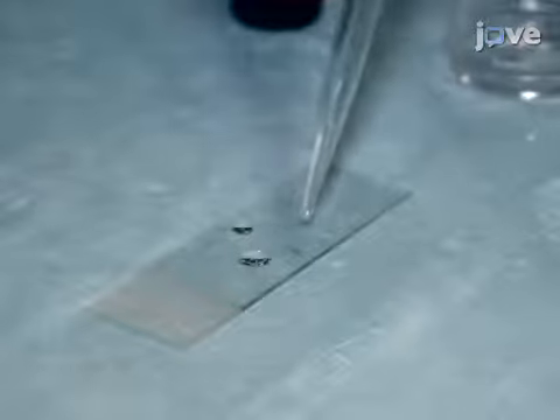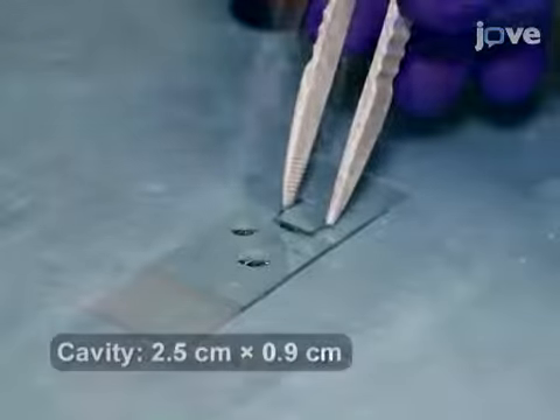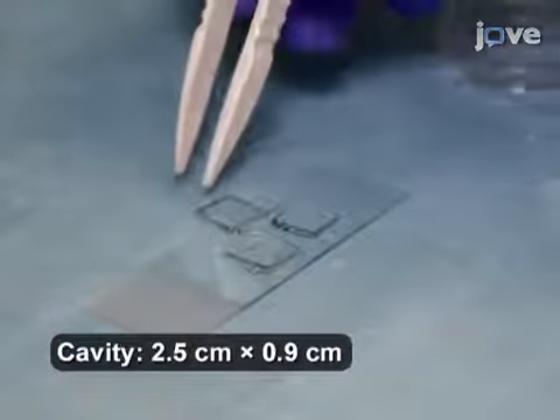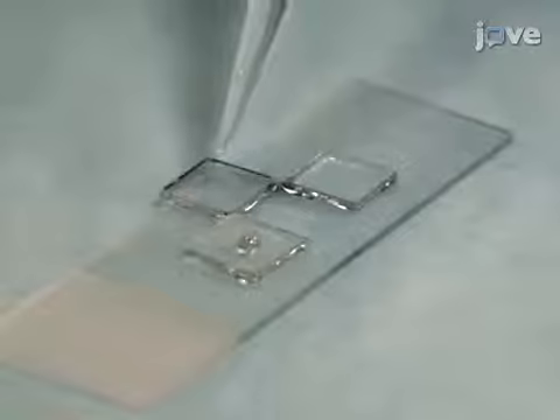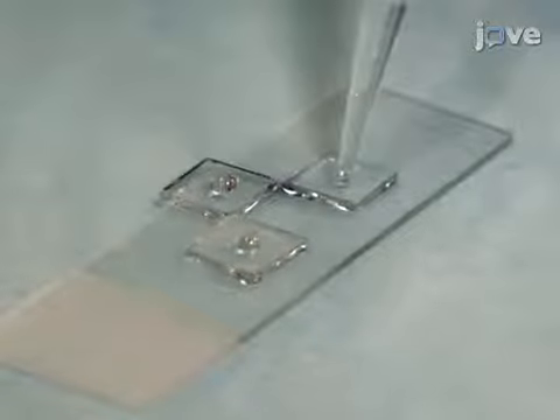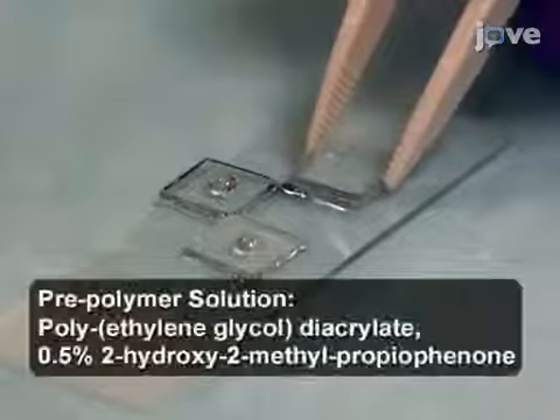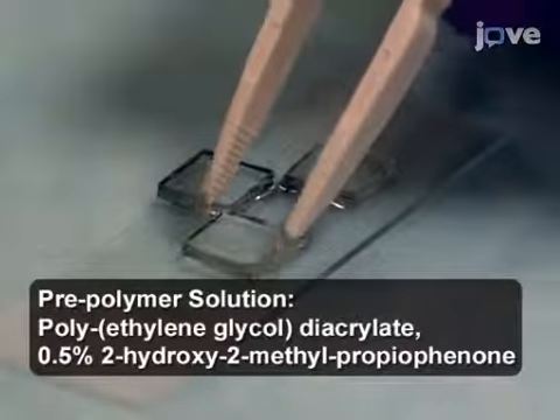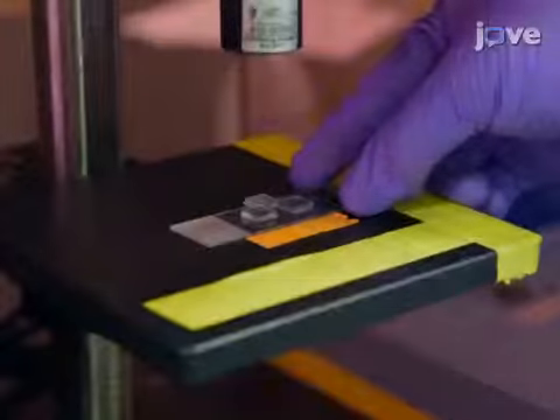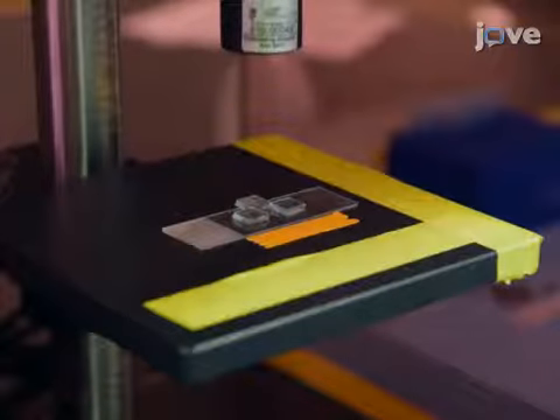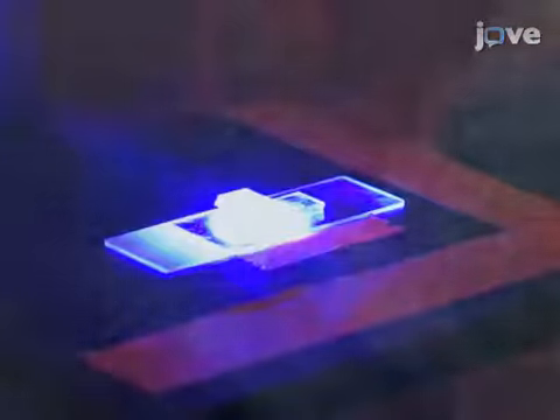Stack glass slides on either side of a rectangular-shaped cavity to set the maximum height of the microneedles. Secure each layer of the glass slide by applying a thin layer of pre-polymer solution onto the glass slides in between each layer. When finished, irradiate the setup with a high-intensity ultraviolet light for 2 seconds to fix the slides into place.